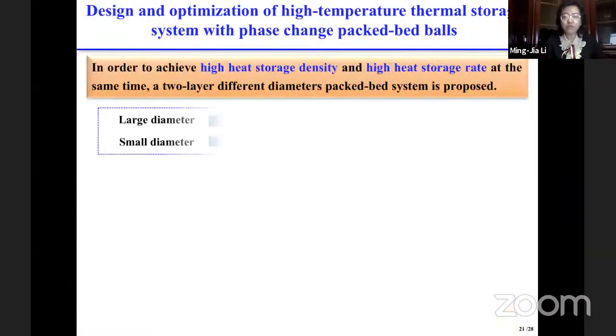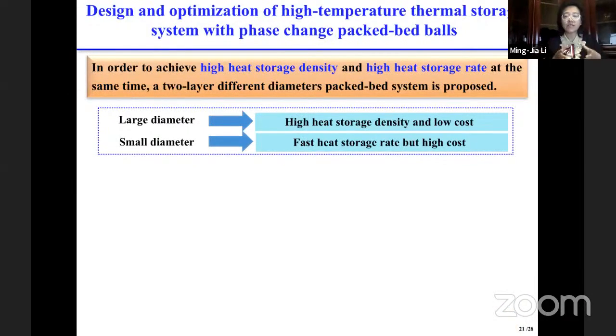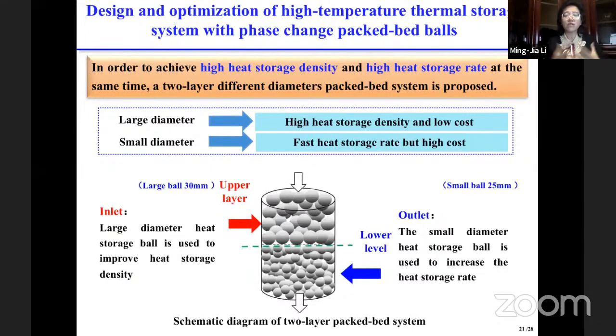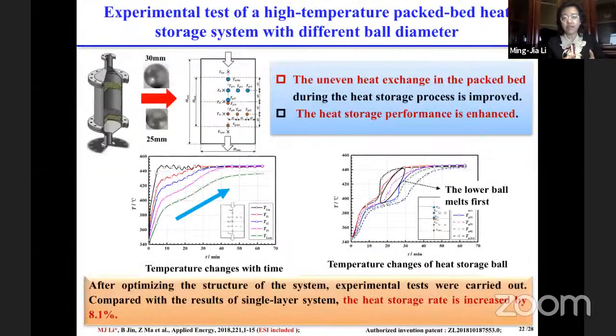What shall we do? Because we mentioned before, we want high density, fast rate, but low investment cost. That's why we finally do the comprehensive optimization. For the upper layer, we choose the larger ball with a diameter of 30 mm, and for the lower layer, we choose the optimized smaller ball, which is 25 mm. We also did the simulation analysis and the experimental test. Finally, the heat storage performance is enhanced and the heat storage rate is increased by around 8%.